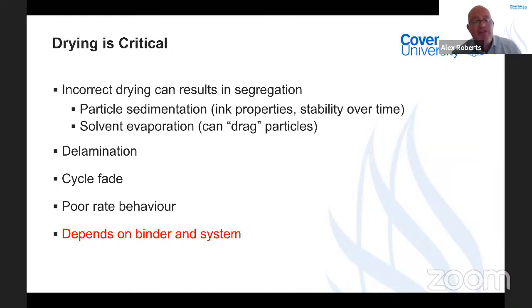And if this drying is done incorrectly, you get problems. You can have sedimentation of particles. You can have critical particles themselves migrating through the electrode. A very good example of this is if you work with water-based coatings with a common system of CMC and SBR. SBR being styrene butadiene rubber, which is provided as an emulsion. These particles, one of their main functions is to stick your electrode to the current collector. And these very small engineered particles can be effectively dragged with the evaporating solvent if you dry too quickly, which can result in delamination of your electrode. You can get other problems around cycle fading, poor rate behavior.